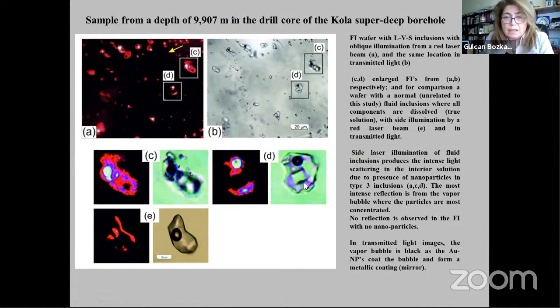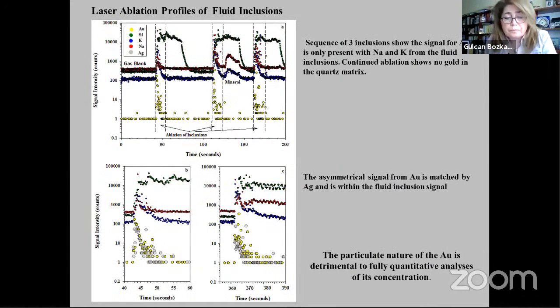Here you can see the salt cube shows no reflection. You can also note that in these inclusions in transmitted light, the vapor bubble appears almost completely black due to a skin of nanoparticles preventing the transmitted light. We analyzed the fluid inclusions with laser ablation ICP-MS.